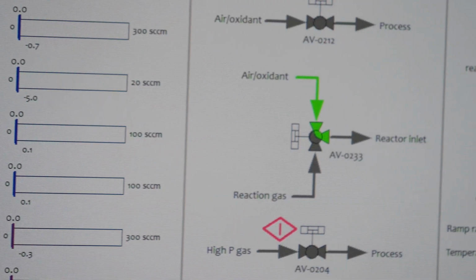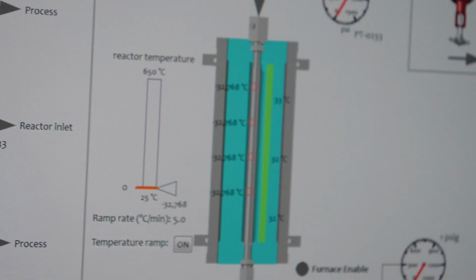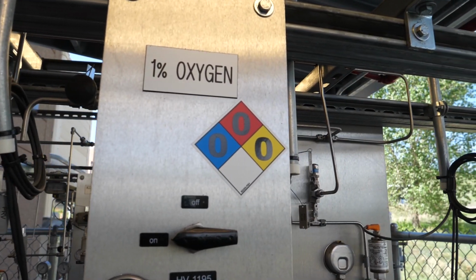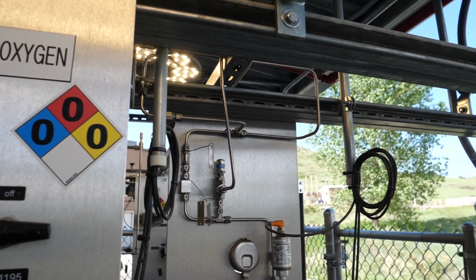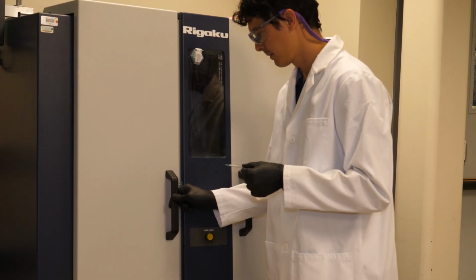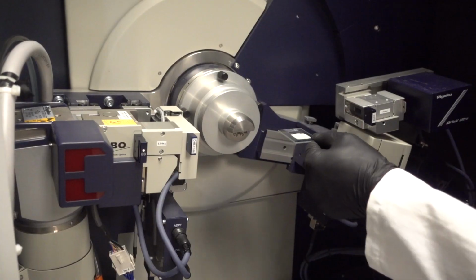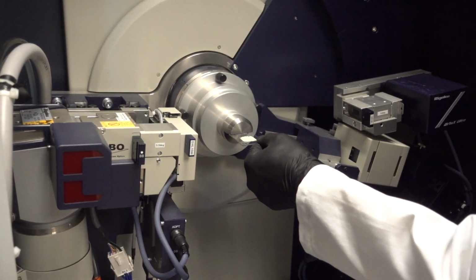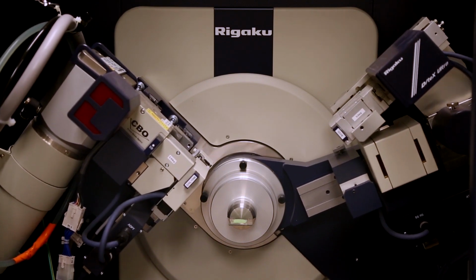Hi, I'm Matthew Young, and I'm a research scientist specializing in materials characterization and catalysis. Catalysts are commonly regenerated through a high temperature oxidation, which can remove carbon deposits that can block catalyst active sites. One of the challenges in regenerating metal carbide catalysts is that they oxidize even under very mild conditions and at low oxygen concentrations. And we see this using in-situ X-ray diffraction. In-situ X-ray diffraction is a technique that allows us to look at the crystalline structure of a catalyst while it's